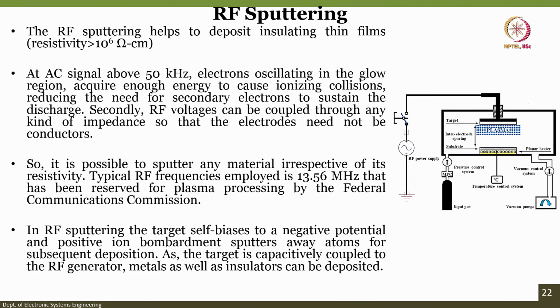If you want to sputter metals, you can go for DC sputtering. If you want to go for insulators, it is better to have RF, because the RF voltages can be coupled through any kind of insulating material, particularly any kind of impedance. The typical RF frequency employed is about 13.56 megahertz, which has been reserved for plasma processing by the FCC.